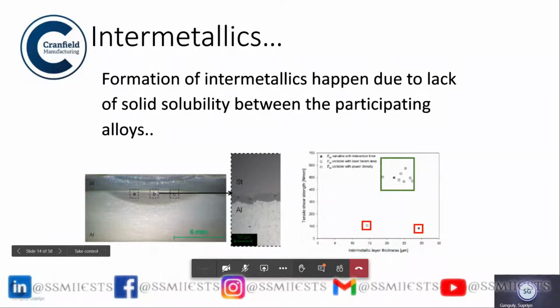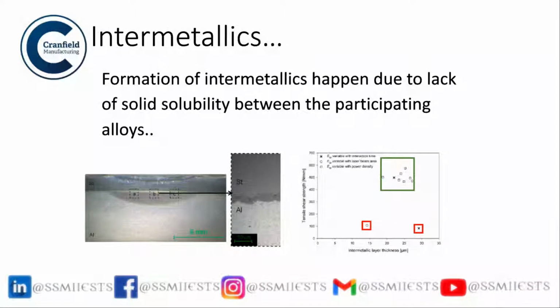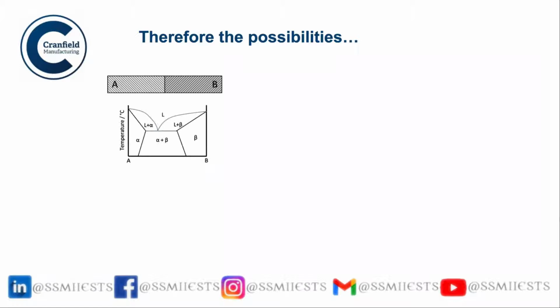Now, this is another graph which shows how the tensile shear strength, on the y-axis, varies with the intermetallic layer thickness. As you can see, even at a lower thickness you can have a lower strength of a joint, because it not only depends on the intermetallic amount or volume, but also on the total amount of wetted area. That is basically studied in this particular research, and we try to form the solution for joining of aluminium to steel.